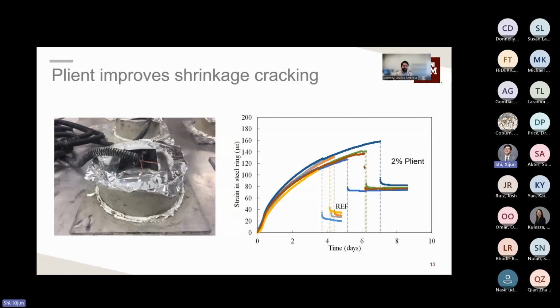And as the concrete is setting, it's starting to shrink. And we can measure the strain development in the ring and estimate as cracks start to develop. We see drops in the strain as it's able to be released slightly. And we can compare the trends between the strain development in time between reference concrete, which is concrete that has no Plient fibers, and a dosage of 2% Plient fibers. And what we see is, first, the Plient fibers are able to achieve significantly higher strain development, but critically, we see a delay in the crack formation due to the Plient fibers, which is showing the Plient improves the shrinkage crack development over time.